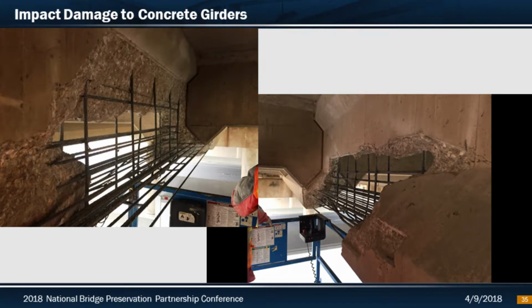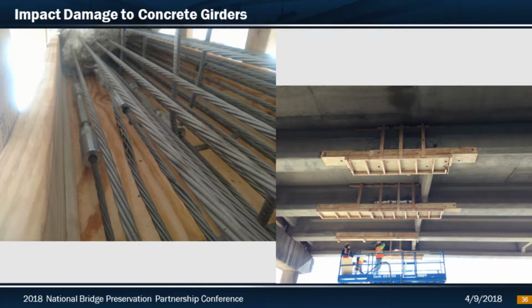The concrete was removed and the surfaces were prepped. You can see the cable splices here. We did leave at least one in this location unspliced just due to the congestion of those Grabbit splices. They tend to take up a lot of space, so sometimes you have to lose a strand to get better concrete consolidation. But you see the steel was blasted clean, surfaces are nice and clean, and again formed up and shotcreted.